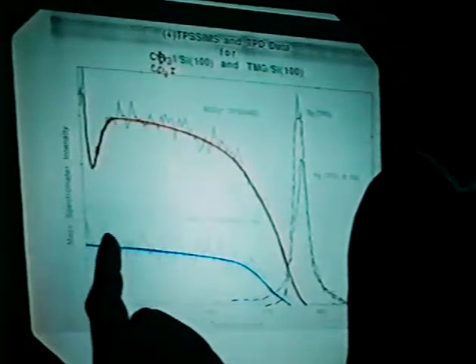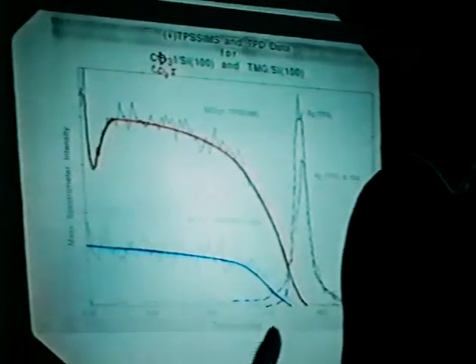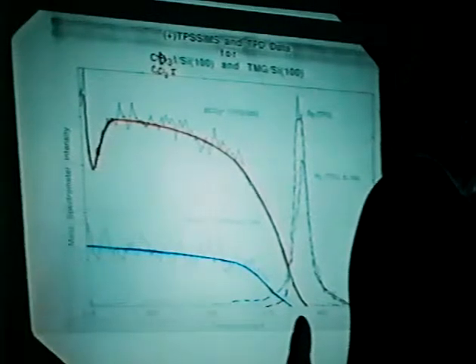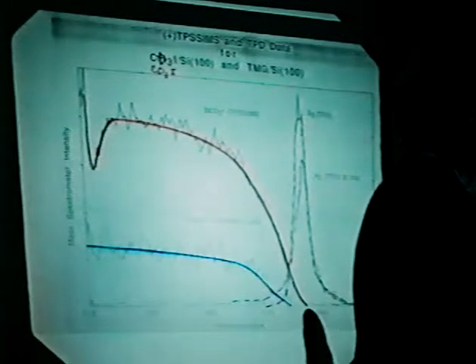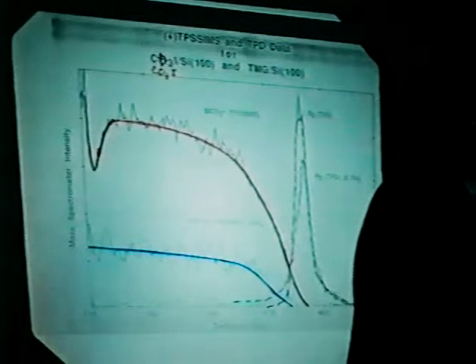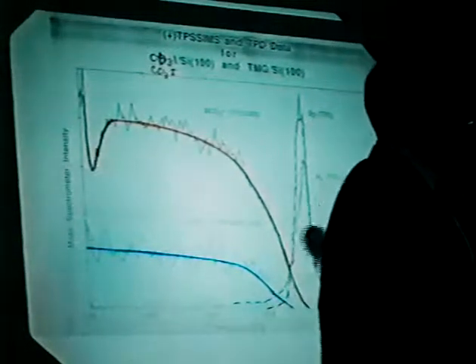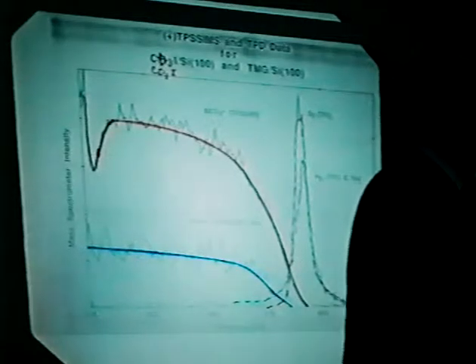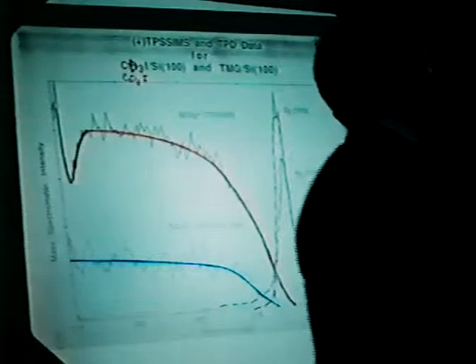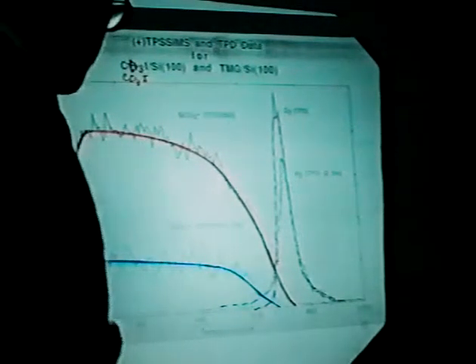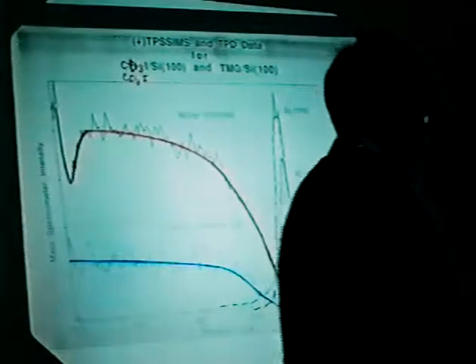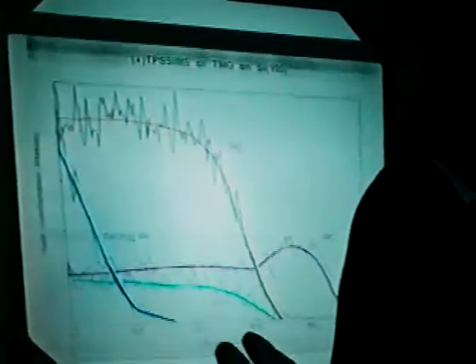Now you see this SiCH3 plus signal. See, it hangs in here. It's relatively stable. Signal to noise is not particularly good, but you can certainly tell that it hangs in there to well above 500 Kelvin and is gone, coincident with the desorption of this hydrogen. So there's a kind of kinetic picture that you get in a transient mode by doing the combination of this static SIMS experiment with the temperature programmed desorption.